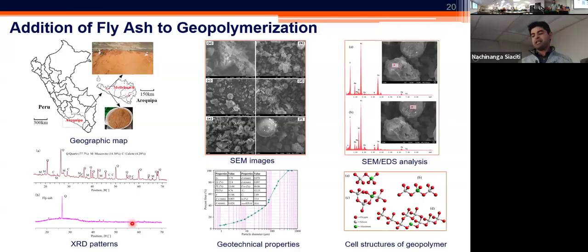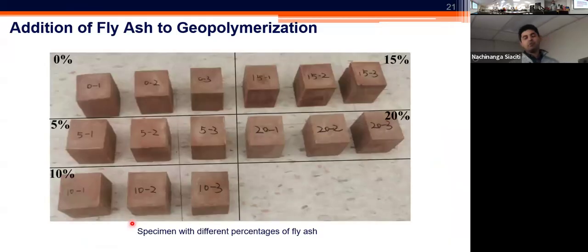So the production process is the same as before. You just mix the fly ash with the tailing, and then you mix it with the activator, and then go through the casting process. Here are the pictures of the specimens that we made, ranging from 0% addition or supplementation with the fly ash all the way to 20% addition of the fly ash. All of these samples look visually the same. They all look solid after they completed the curing process. And by the way, I should have mentioned that the curing process is usually 1 week long. So we put the samples in the oven, first at 40 degrees Celsius, followed by about another 7 days of curing at 70 degrees Celsius. So that's what we did for these steps that are shown here.